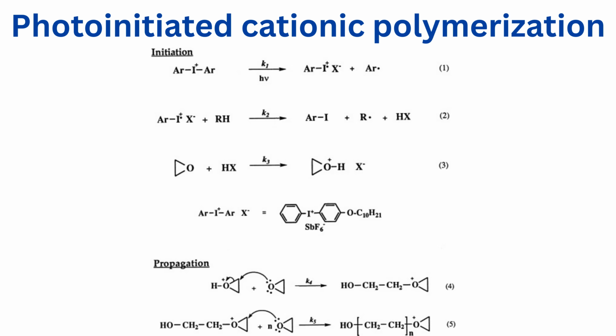In general, a photopolymerizable formulation contains three key components. 1. A photoinitiator, which absorbs the light and generates the active species. 2. A reactive multifunctional monomer or oligomer, or a mixture of both, that gives rise to a cross-linking polymerization. The backbone of the oligomer can be varied widely and is designed to confer specific mechanical and physical properties to the polymerized material. 3. A reactive diluent, the role of which is to adjust the viscosity of the mixture to an acceptable level for application to a substrate. It also participates in the polymerization reaction.